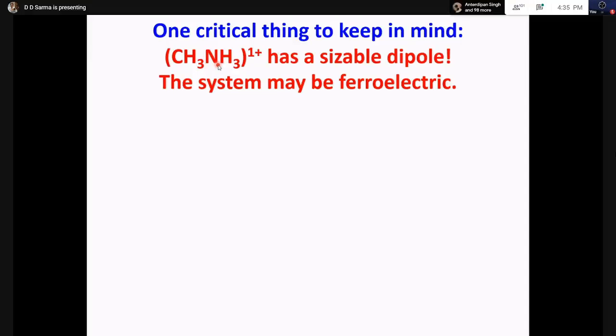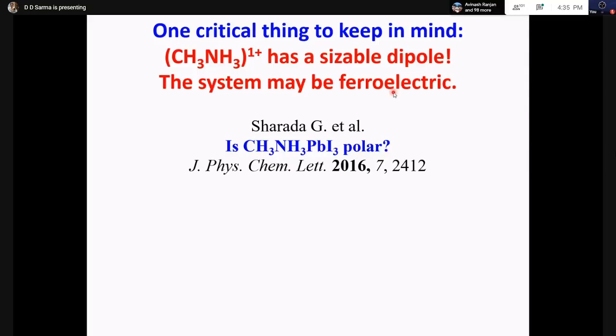So if these order, they can order either in a ferro fashion, aligned, so that the overall crystal structure will be non-centrosymmetric, and the entire system will have a polarization because the dipoles are going to arrange, and that means it will be ferroelectric. Or they can arrange in such a way that one dipole and the next dipole cancel each other's dipole moment, which is called the anti-ferroelectric arrangement, and then it will recover its centrosymmetry in the crystal structure. That's why Sharda very early asked the question, is it a polar structure? That means, does it have a center of inversion or not? Do the dipoles align, or do the dipoles anti-align with respect to each other?